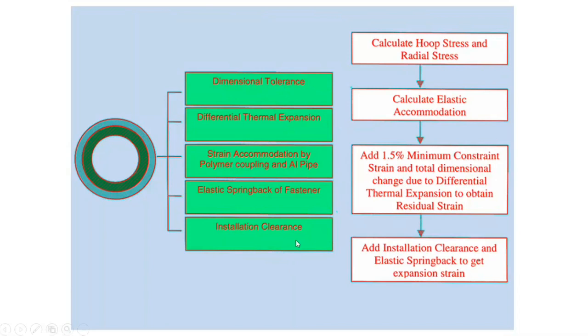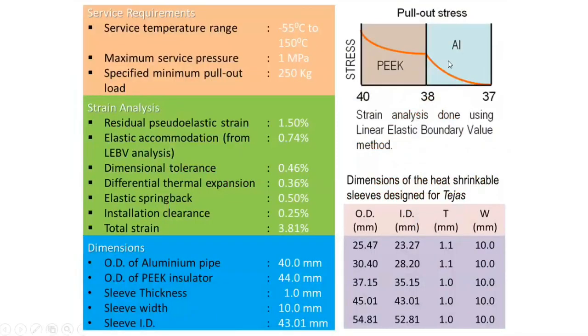So you got 3.81% strain to play with, which is lost towards dimensional tolerance, differential thermal expansion, elastic spring back, which means to say you deform it in liquid nitrogen, and when you let go you lose 0.5% strain, and some installation clearance, like 50 microns, but we can do with 25 microns if the situation is bad. So it's something like 25, 50 microns. So you can do all this to calculate the dimensions of the coupling or the ferrule in this case, just to show how you calculate these things. You have got a pull-out stress, and that you know already, and from which, knowing the decay, you know what the stress that needs to be applied, and if you know the coefficient of friction and all that, you can work it out with some kind of safety factors.